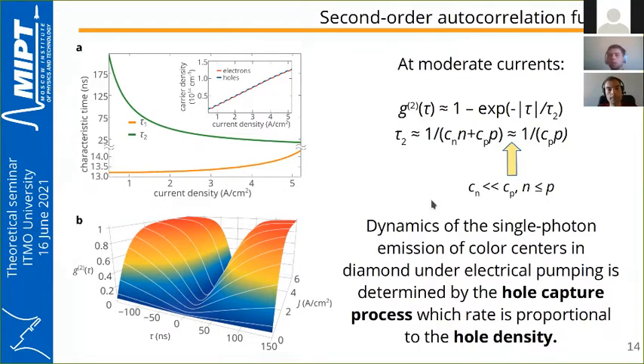What we need to do is measure the G2 function from the color center and measure the dip width of the G2 function. After that, we can just divide by Cp and obtain the hole density near the color center.